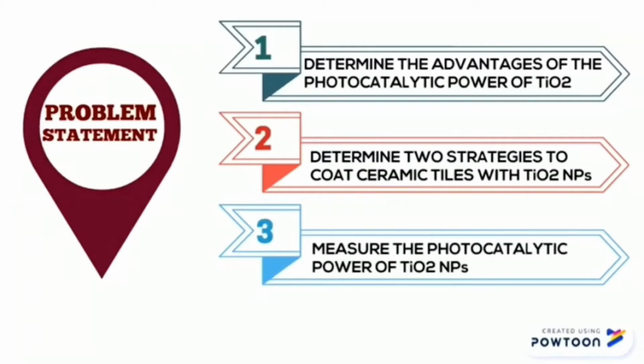Coating a surface with titanium dioxide, a material with high photocatalytic power, helps in self-cleaning properties and decomposition of pollutants. The two methods being used are simple heat treatment and APTES treatment, which is coating the tile with titanium dioxide particles. In the second method, titanium dioxide nanoparticles are aminosilanized using APTES treatment and then covalently attached onto carbon dioxide plasma treated ceramic tile via EDC and NHS chemistry. It is then monitored using dynamic light scattering, DLS, and X-ray photoelectron spectroscopy, XPS. So this is how the proposal works.